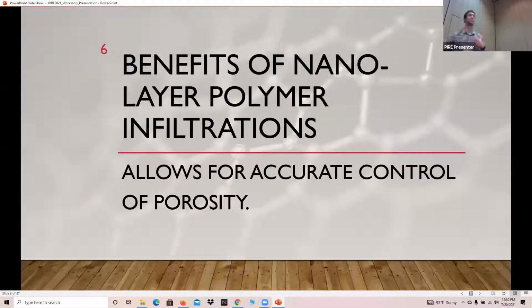This allows for the benefit of a highly controlled porosity. For the 500 nanometer layer, we can do it in a fairly quick cycle that allows for a buildup of a full matrix, or around, say, a woven pattern that has particulates in it, and we can build up the matrix in that manner. For the slower process, say reduced to 0.1% of SMP10 to hexane, we can build up slower, so we can allow for controlled porosity, which in turn controls permeability for transpiration cooling applications.